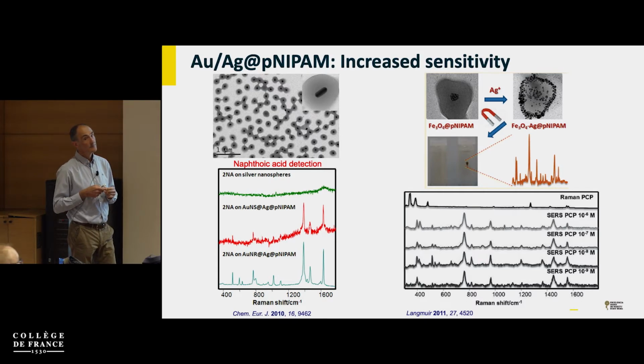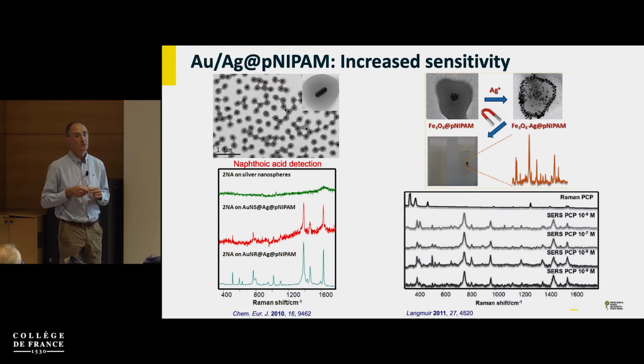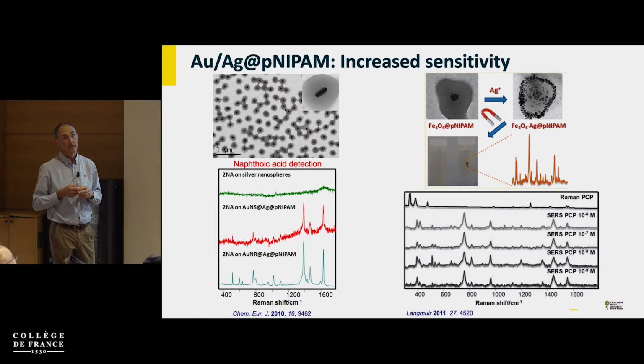How many measurements can you perform with one batch? Many, because it depends what type of sample you want to measure. But typically these measurements, if you do them in solution, you only use like 1 or 2 milliliters. The production is done in hundreds of milliliters. And you can even fabricate a larger concentration and then dilute in little batches, depending on the concentration that you want to detect and the signal that you can obtain.